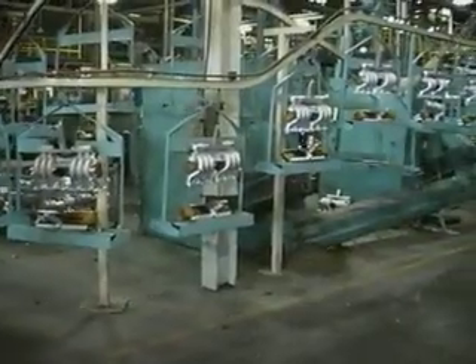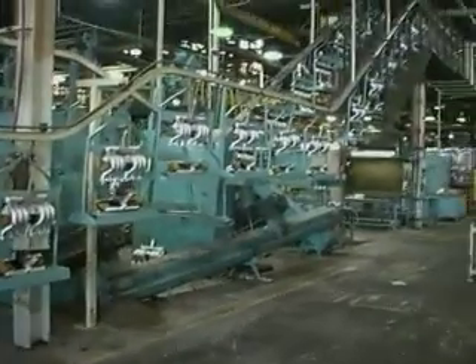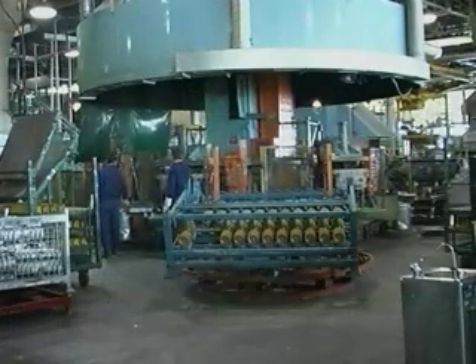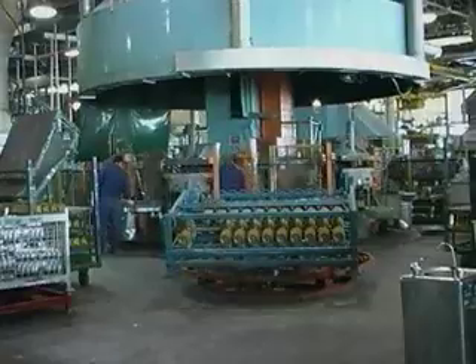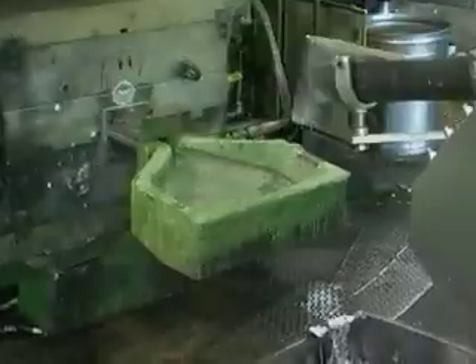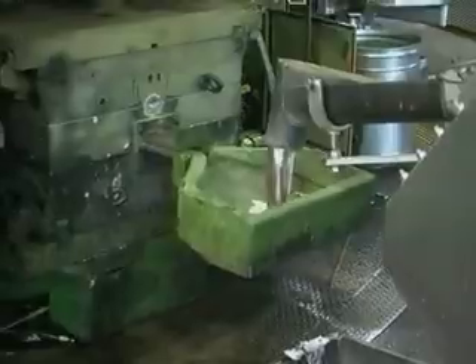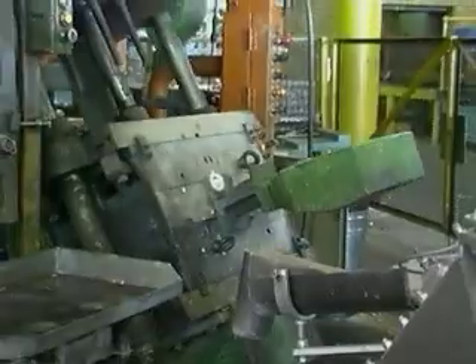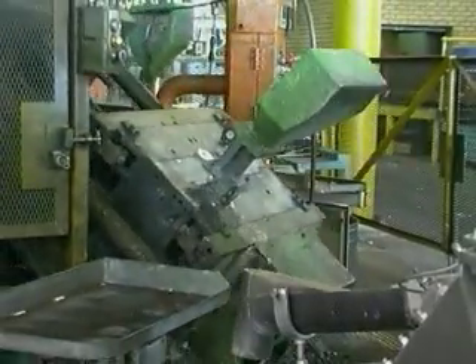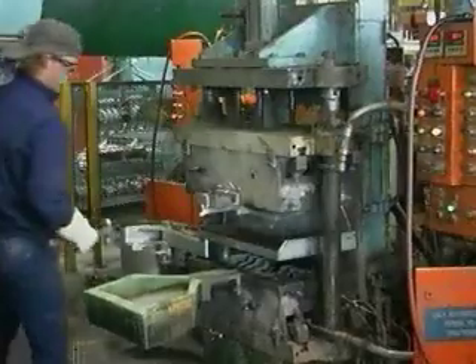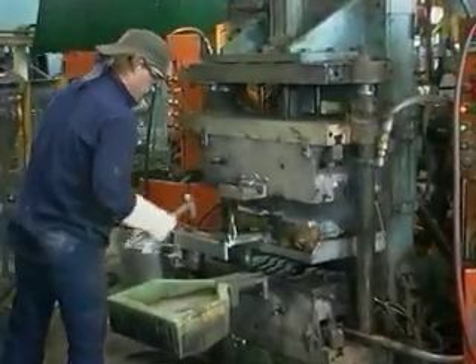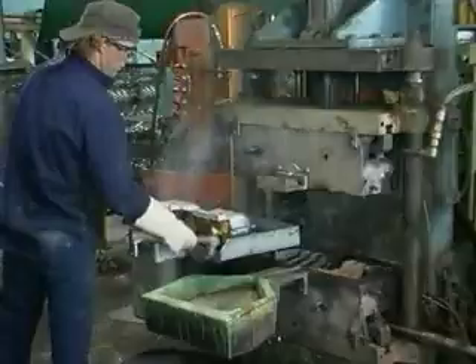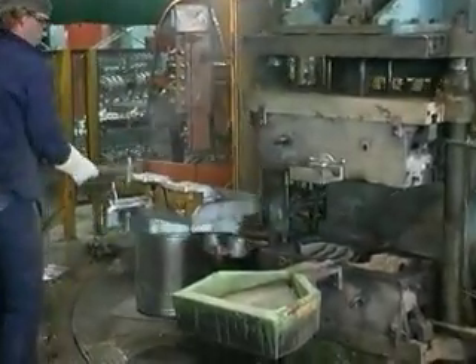In the automotive industry, large numbers of cast aluminium manifolds are required. To produce these, the tilt casting process has been largely automated by putting 12 casting machines on a carousel. The 700 kilogram capacity dosing furnace delivers an exact quantity of aluminium alloy into the launder. The die tilts back as it moves around. When the metal has solidified, the die tilts forward and opens, allowing the casting to be removed. On this carousel, 2 different manifolds are being made at the same time.